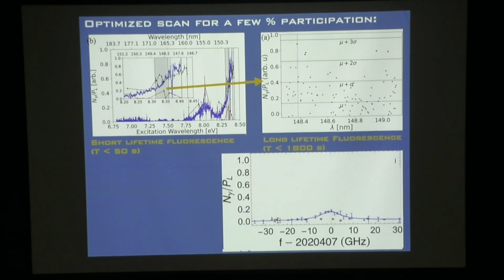Then we said, okay, well, if this is thorium-229, let's put in the thorium-232 crystal. And we don't see anything here. Now, that's exciting, but it doesn't have to be the nuclear transition. It could still be some sort of weird defect, although this is really narrow already for a defect. Let's put in another 229 crystal. And we grabbed a crystal off the shelf which had less thorium in it.